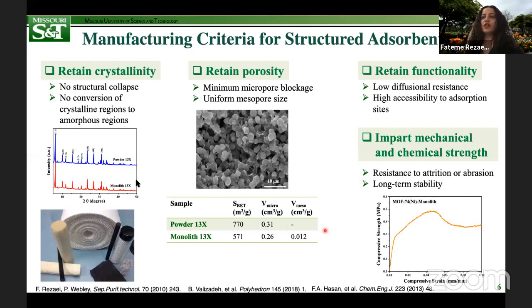We define several important manufacturing criteria for structured adsorbents, regardless of the shape. These include, but are not limited to, retaining crystallinity, which means no structural collapse or conversion of crystalline regions to amorphous regions should take place during formulation or fabrication of structured adsorbents. The other criterion is retaining porosity, which dictates minimum micropore blockage and uniform mesopore size distribution for our structured adsorbents. Retaining functionality is another important manufacturing criterion, which, as expected, means we need to have low diffusional resistance and high accessibility to adsorption sites for our structured adsorbents. And finally, impart mechanical and chemical strength, which means that the structured adsorbents must be resistant to attrition or abrasion, and they should also exhibit long-term stability.